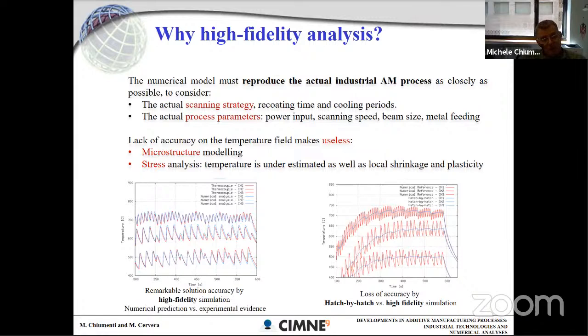So they did a lot of hardness experiments to compute the hardness, and they compared it to the microstructure evolution, and they also related this to this cooling time, so the time spent in this alpha beta period, and the correlation is quite good. Not that much in SLM, because in that case, the cooling rates are too fast and typically you obtain martensite. But if you work with wire feeding or blown powder, this works quite well.